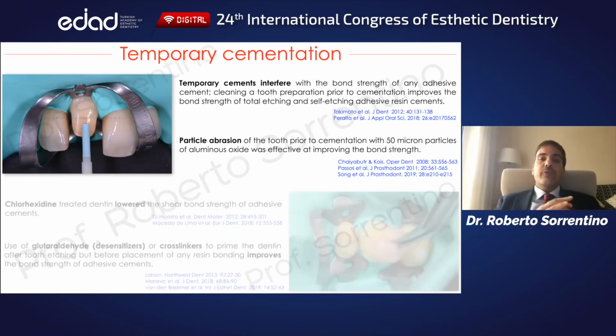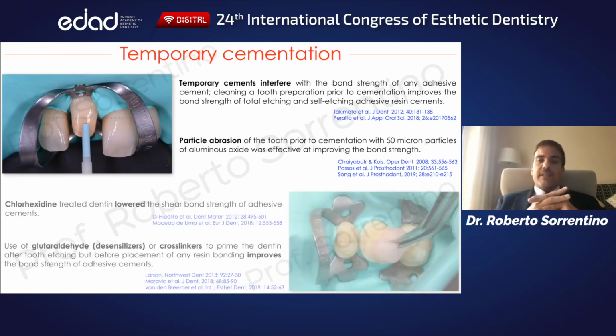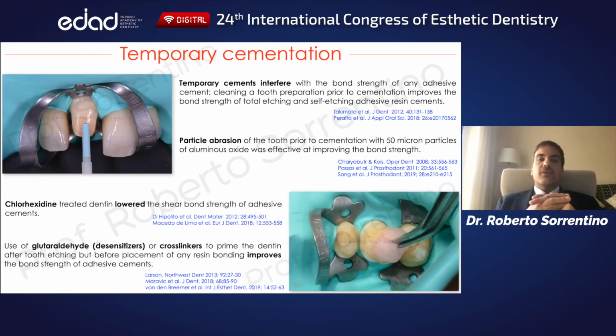Moreover, as regards antibacterial activity, the role of chlorhexidine is controversial, and it can lower the final bond strength. So glutaraldehyde cross-linkers, just like cleansing agents, desensitizers, and adhesion enhancers, should today be preferred to prime the dentinal substrate.